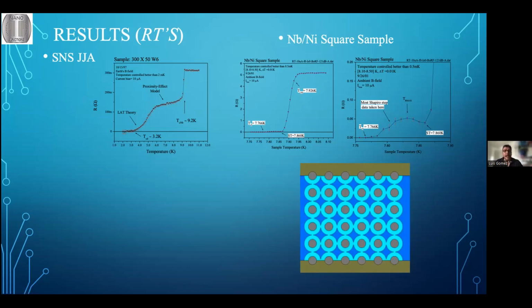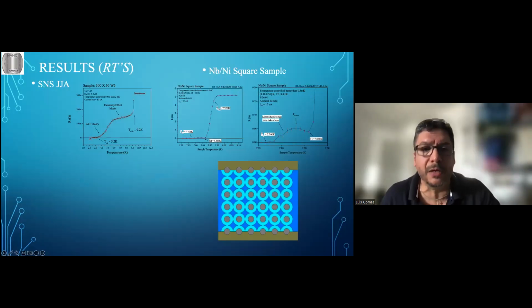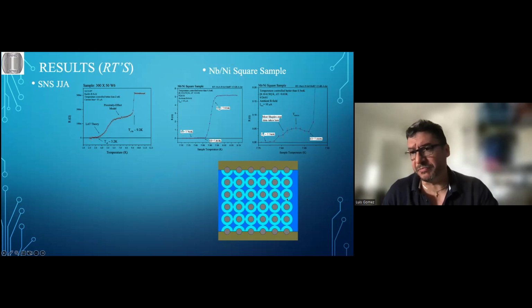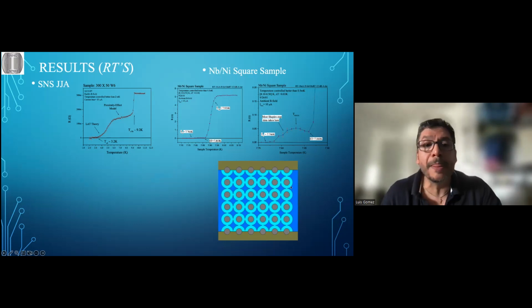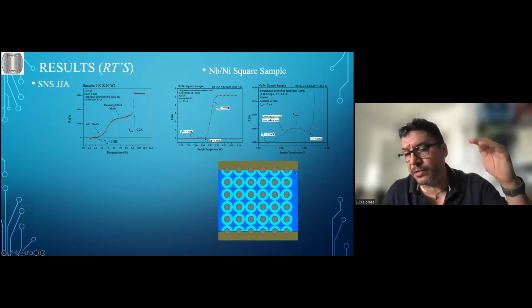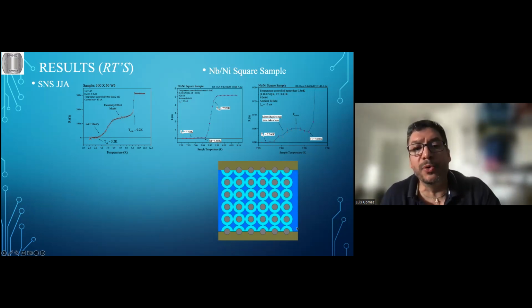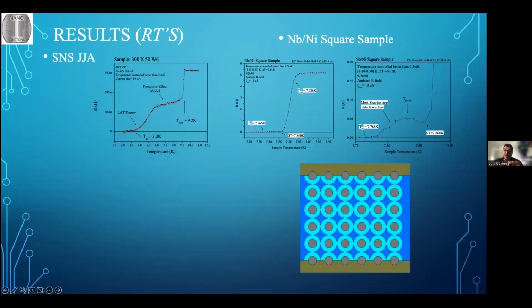From above we see the substrate, this kind of dark yellow color, and then you see the orange coins or circles. Sorry, the gray circles. This is the nickel, and then on top we have these two different colors of blue. A darker blue, which represents the niobium farther away from the nickel, and a pale blue, which represents the niobium closer to the nickel. So we think that this is the picture somewhere around this region.